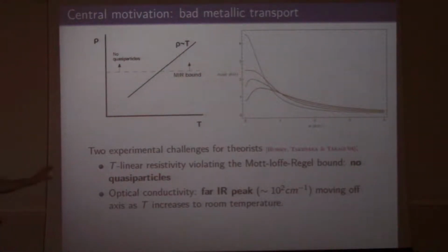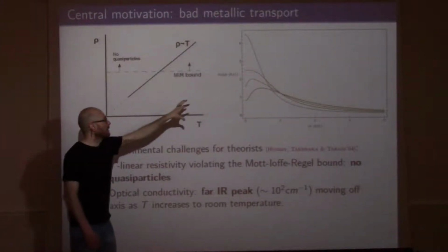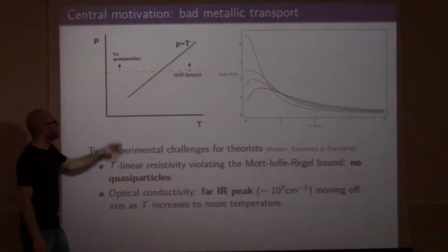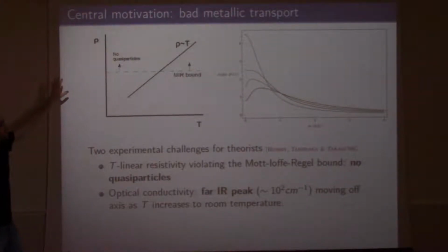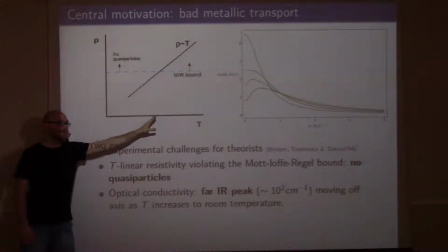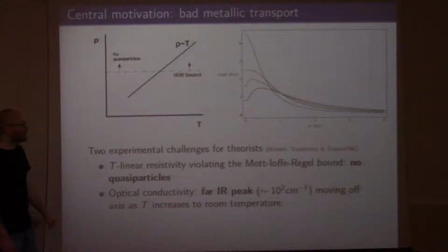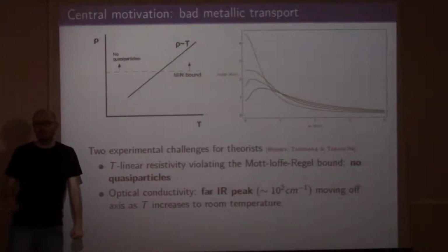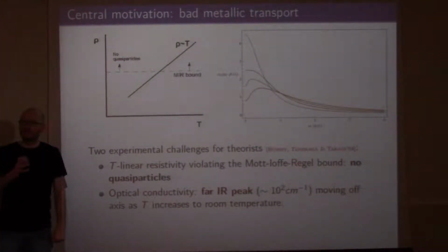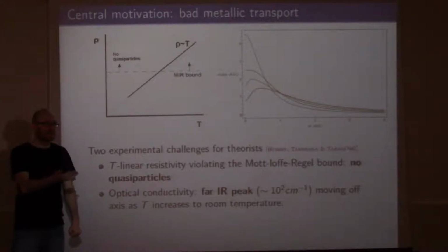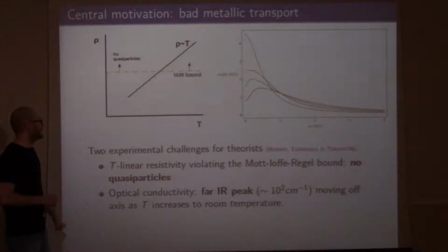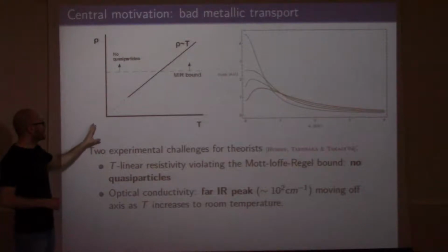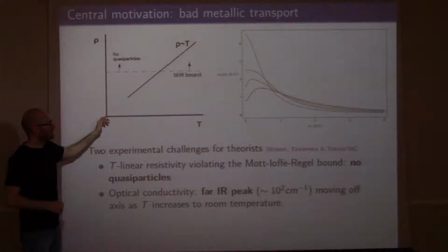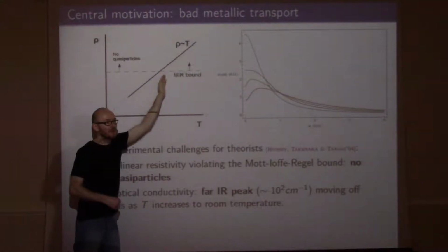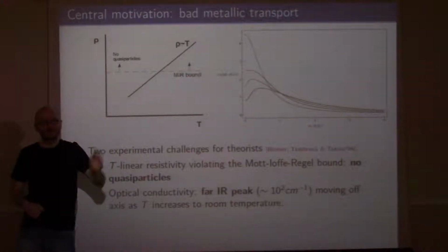Okay, so what's the motivation? The motivation is to try to understand what's going on in these two plots. So the left-hand plot is a plot of the resistivity, the DC resistivity as a function of temperature. And what happens in many so-called bad metals, so these are specific compounds, but I won't really tell you exactly what they are. Let's just say that they exist. And what happens in these compounds is when you measure the resistivity, you find two things. First, you find that it's linear in temperature across many decades or even hundreds of kelvins.